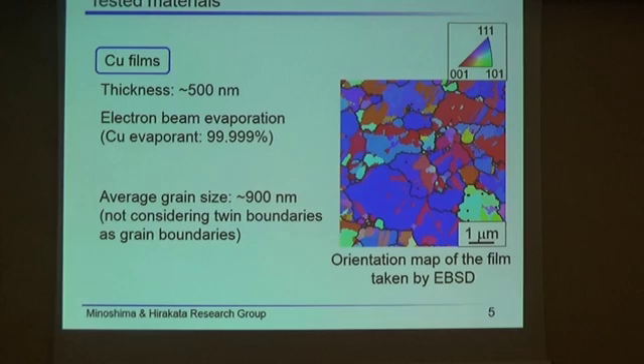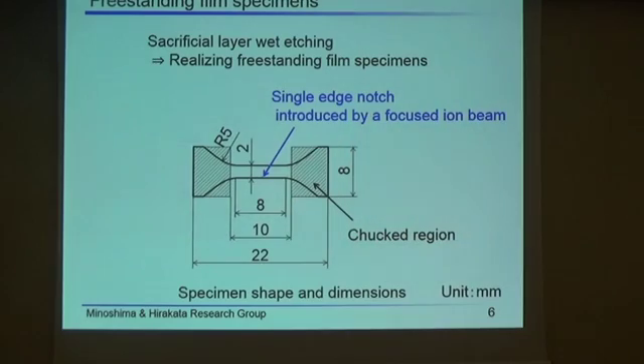Tested materials are copper films with a thickness of approximately 500 nanometers deposited by electron beam evaporation. This is the orientation map of the film taken by EBSD. Black lines indicate grain boundaries, and twin boundaries were observed within each grain. The average grain size is roughly 900 nanometers. And after the deposition, we conducted sacrificial layer wet etching to realize freestanding film specimens.